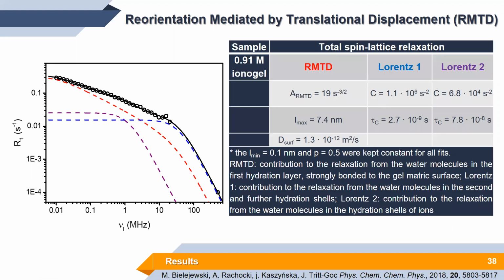And what are the parameters? Well, it was something we could expect, but we actually thought that it may be different. The surface diffusion coefficient of the solvent at the surface of the gel matrix is like 10 to minus 12 square meters per second.